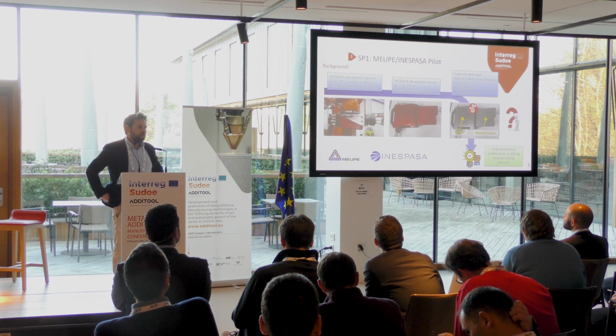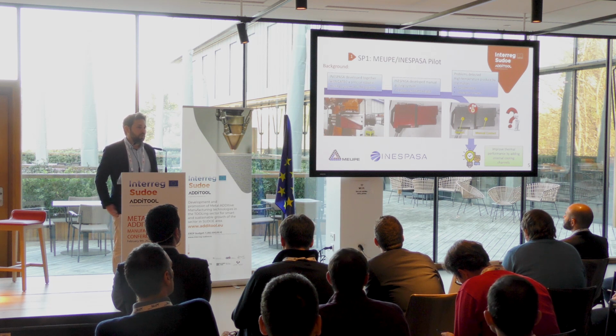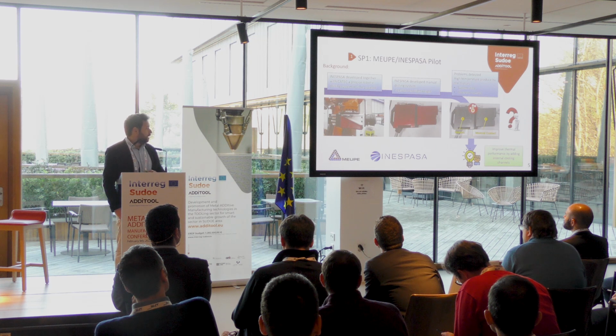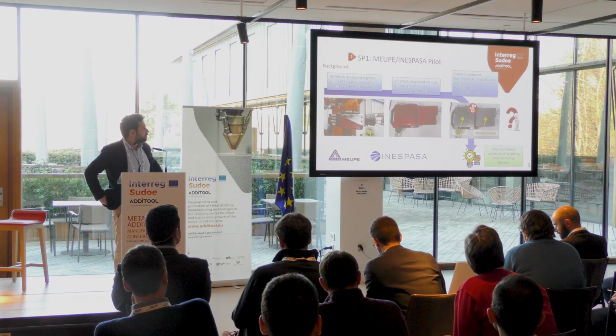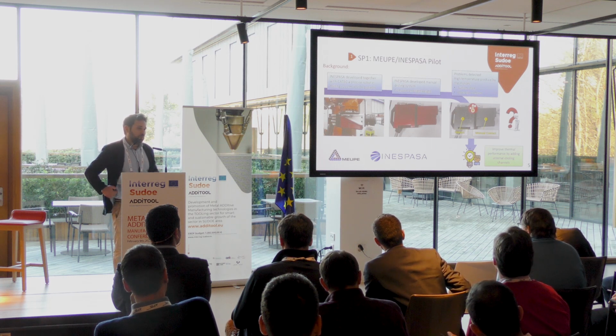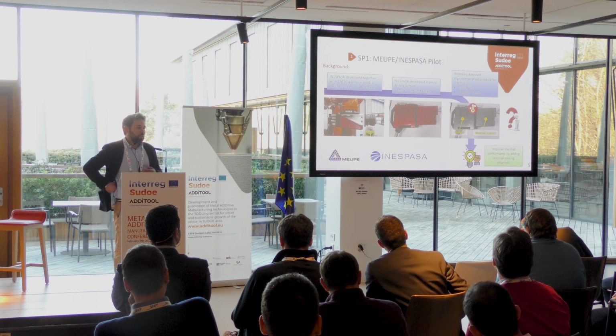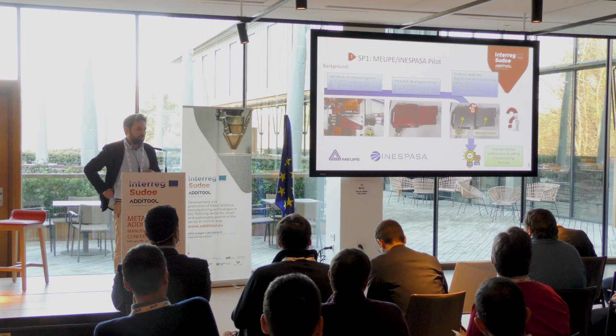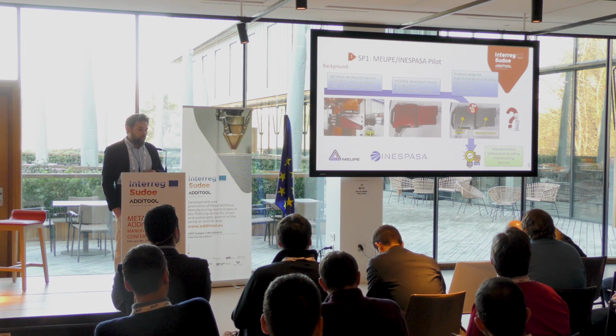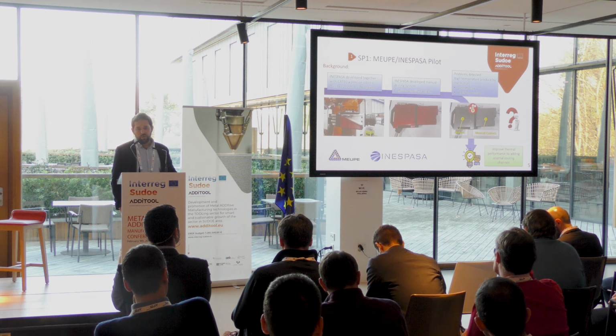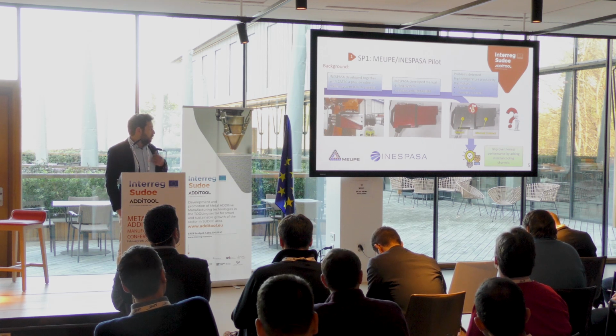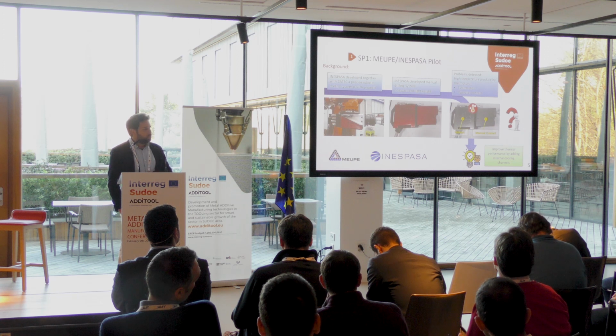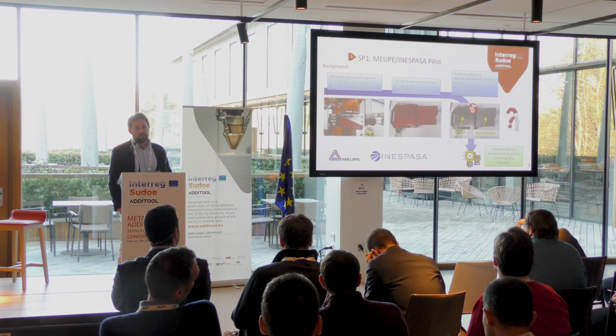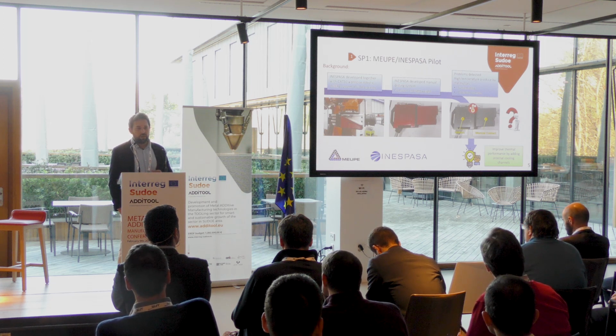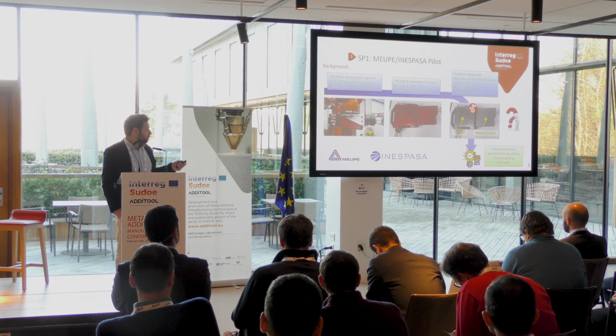That solution also brings some problems regarding the heat dissipation inside the system, because the motors produce high temperatures on the surface, which has to be touched by the operator. It can burn. It reaches like 60, 65 degrees, maybe 70 degrees in operation. Also, if you use high revolutions per minute, the motor can stop. So that was the problem to solve. In our case, we proposed to Inespasa to use metal additive manufacturing with internal cavities and maybe some lattice structure like fins to dissipate that heat and improve the performance.